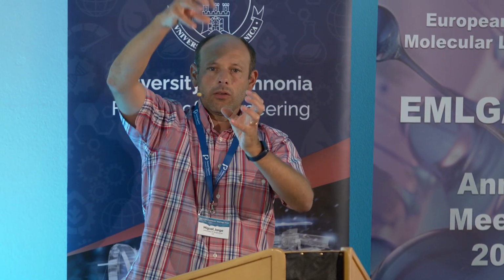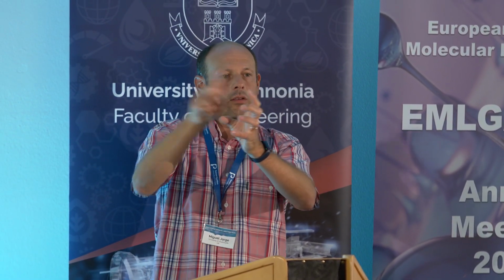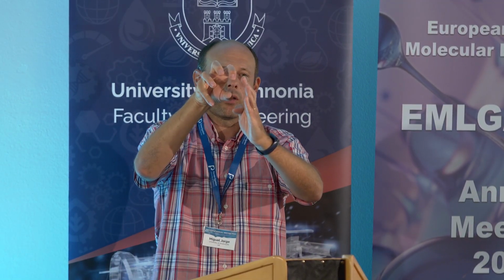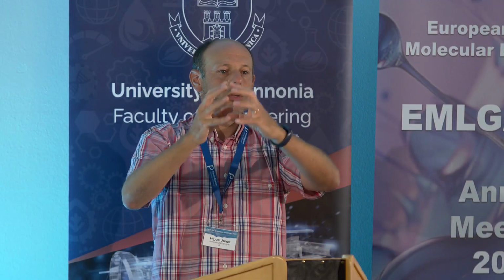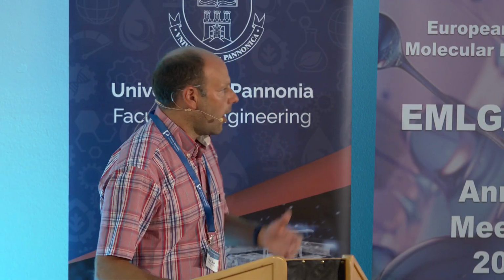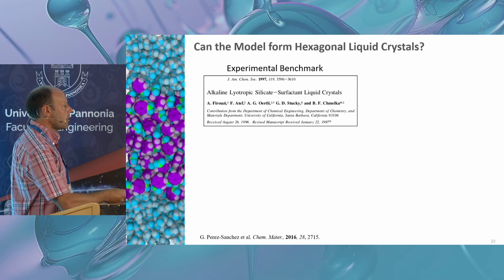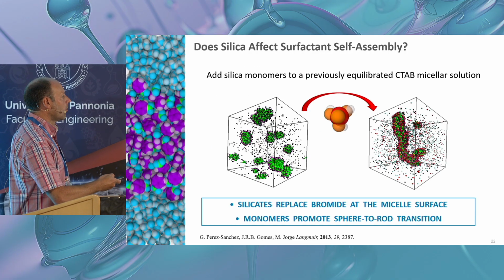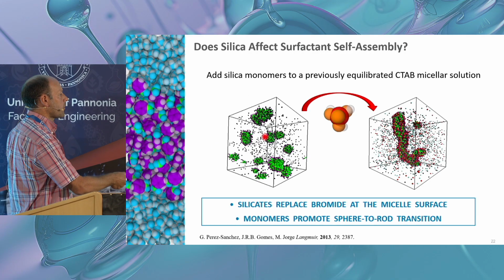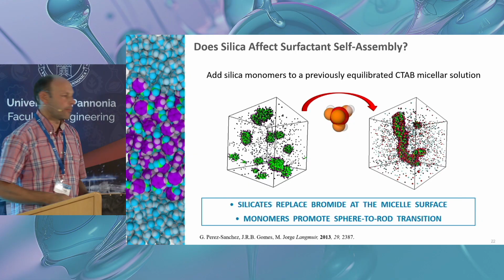the aggregate. If you now add a counter-ion to it, it screens the repulsion between the head groups, so they can now come closer together, mediated by the counter-ion. So you reduce the area per head group, you decrease the curvature. That allows you to form these elongated micelles, whereas without silica, it would be a spherical aggregate, right? So you're reducing the curvature.